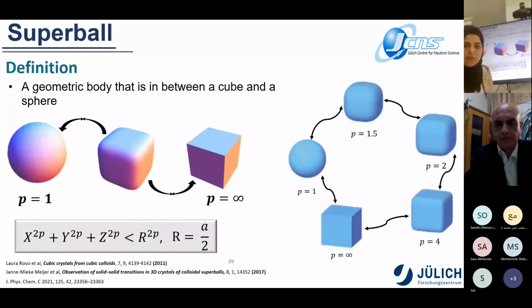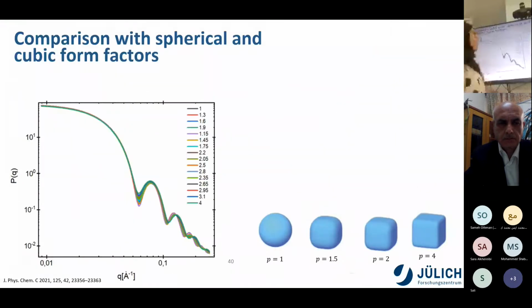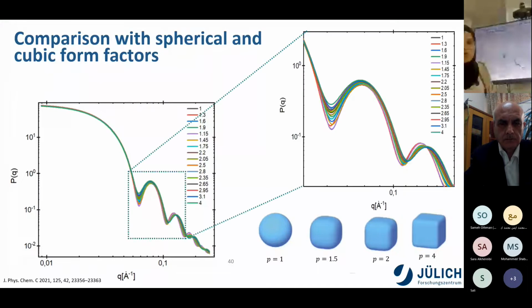We also did some simulations for such a shape, and here is how it looks for p equal to 1, 1.5, 2, and infinity. To compare it with the perfectly cubic and spherical form factors, we also did some simulations here, going from 1 up to 4, and we see that as we go up to 4 the first minimum goes up, but for 1 it's down, as for a perfect sphere.